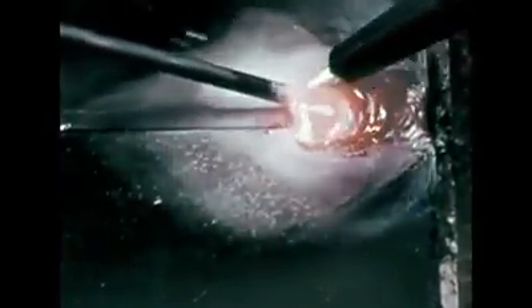Use the same blowpipe and rod motion learned in the last exercise to move the puddle across the sheets and melt both edges evenly. If the molten puddle is moved too rapidly, the weld bead will be too narrow. If the puddle is moved too slowly, the bead will be too wide and may even burn through the sheets. Hold the blowpipe at an angle of 45 degrees to the workpiece to allow preheating of the joint, even rod deposit, and control and movement of the weld puddle in a continuous operation.